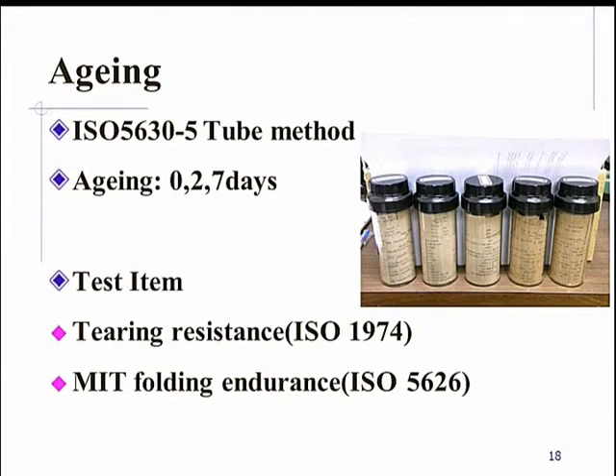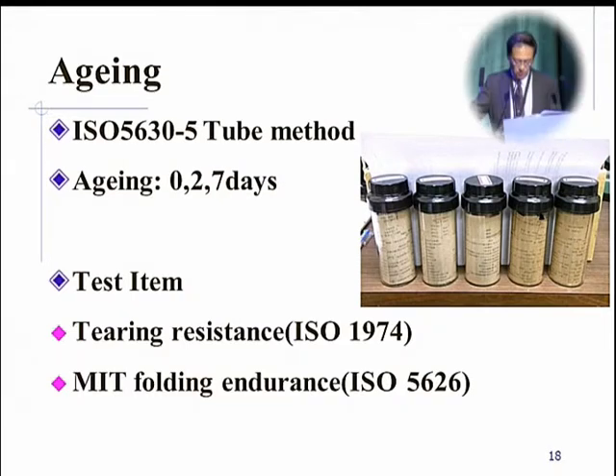Accelerated aging is performed at the Tokyo University of Agriculture and Technology in compliance with ISO 5630-5 using a glass tube at 100 degrees. The time periods used for artificial aging are 0, 2, and 7 days.